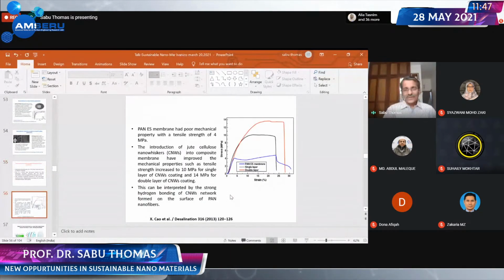Now I want to show you another work, of Professor Ko. He's very active in making filters. According to Professor Ko, many of the membranes that you get from the market all have weak mechanics. Look at this polyacrylonitrile membrane, electrospun membrane, very weak. These are all electrospun. But if you give a coating with the nanocellulose, this is one side coating, look at the strength. The strength goes up. Both side coating, red one. So typical commercial membranes could be made stronger by coating with nanocellulose.